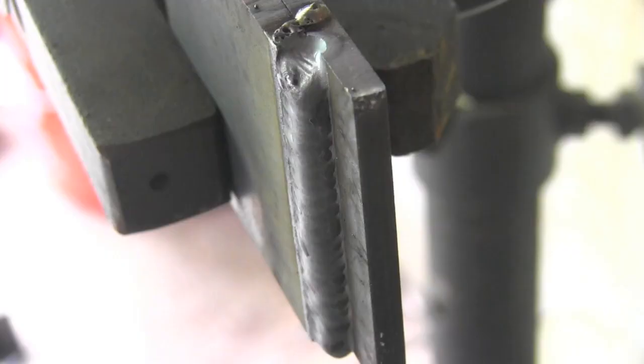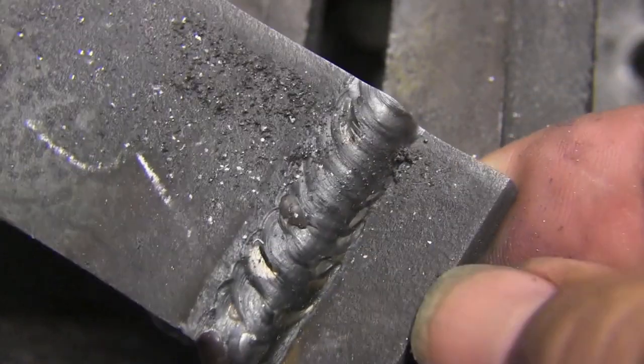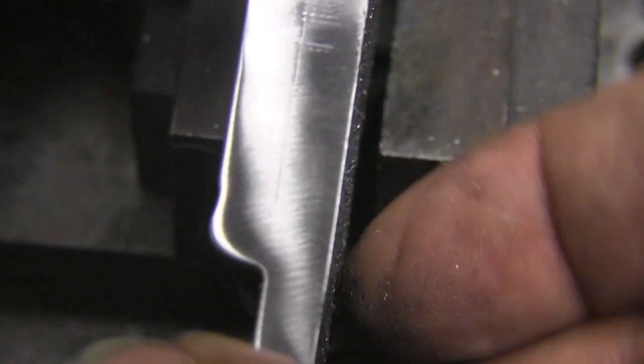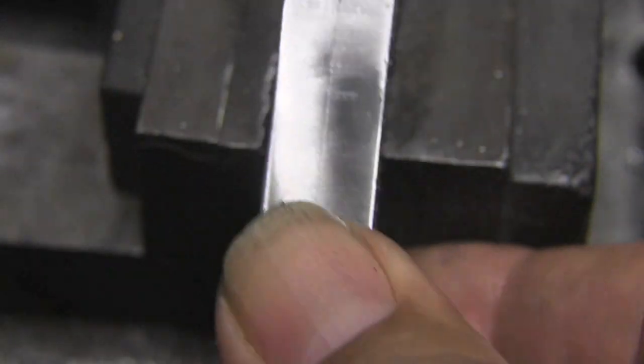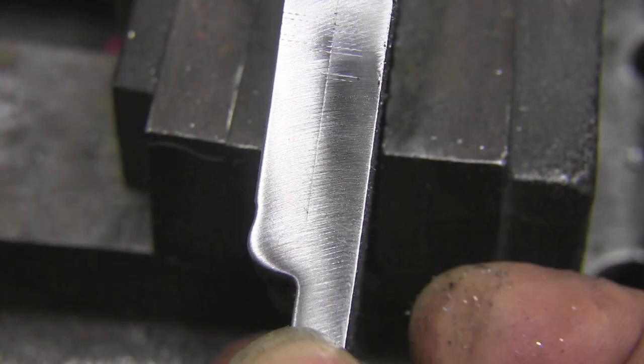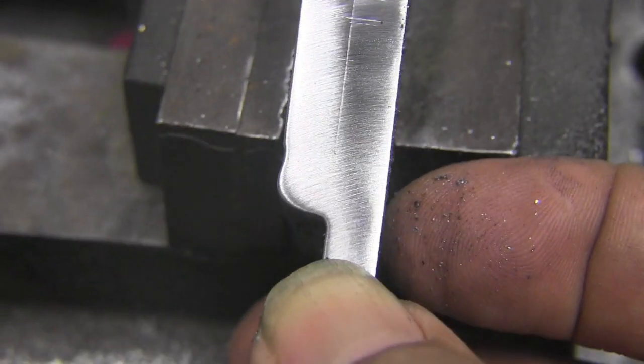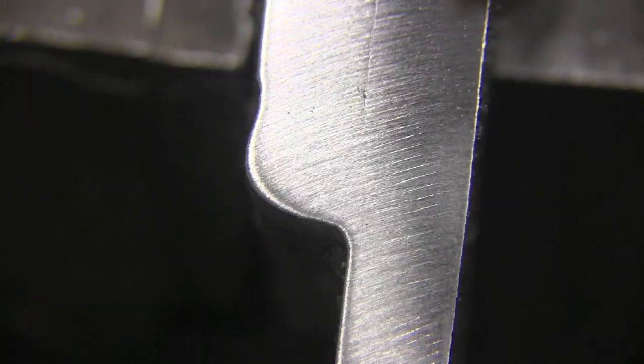That looks like this. Again, that's 18.5 volts and only 211 inches a minute of wire with .035. That's 0.9 millimeter wire, ER70S6, using 75-25 gas through this whole video. Not bad looking, but it's got quite a crown on that weld. Stood up there kind of high. That's not going to be acceptable in some instances. For some, it wouldn't matter. I'd rather have that crown there and have a good weld than a nice flat weld that was a caulk bead, basically. So let's swab etch that and get the results.